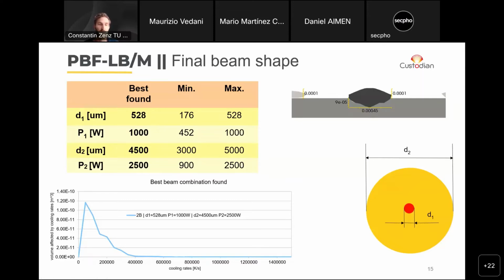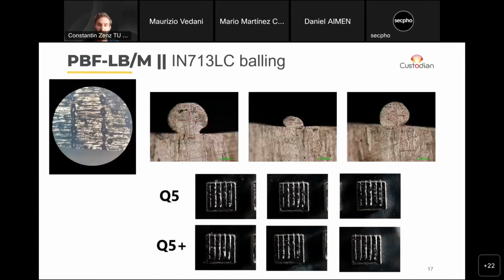So there's also a trade-off and then an optimum that was found. And then let's quickly look at the Inconel 713 LC material. Here the optimization looked quite similar, but in the beginning, in the experiment, it was found that there was an issue we've referred to as balling, so that these are results from